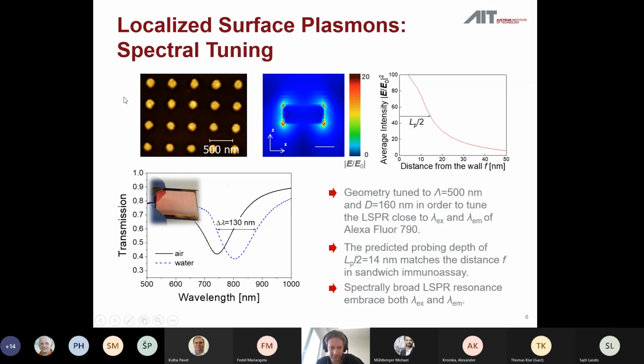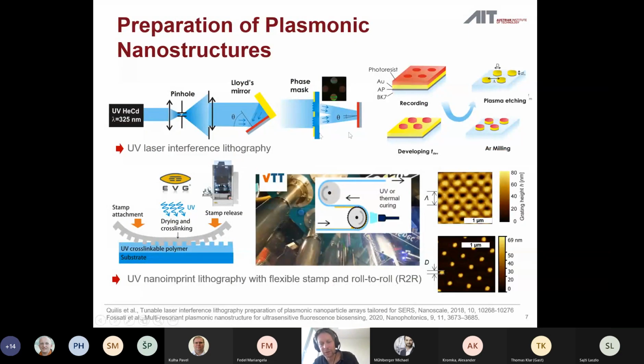And this coupling of light to localized surface plasmons is spectrally sensitive, and it occurs only at certain wavelengths, and that's why these structures can be seen as vivid colors when you attach them, for instance, to a glass substrate, like in this case.